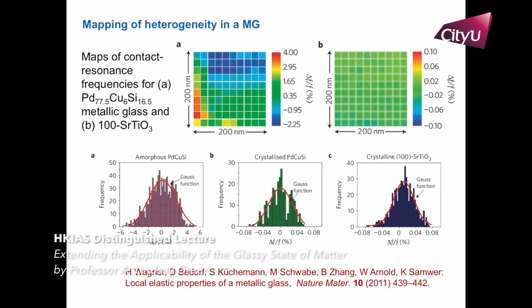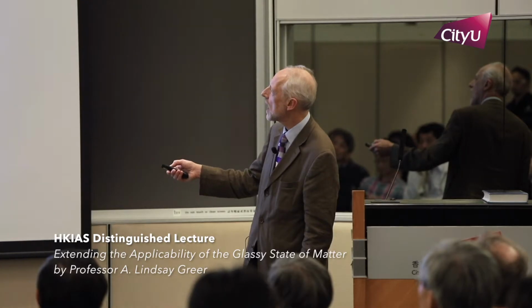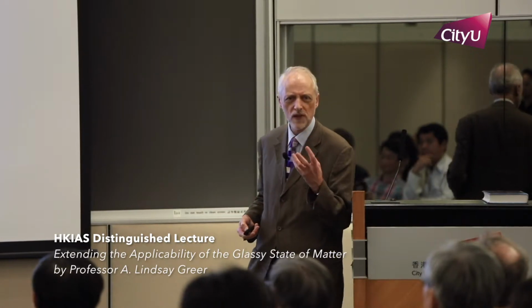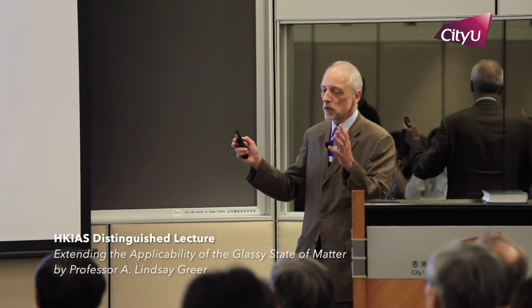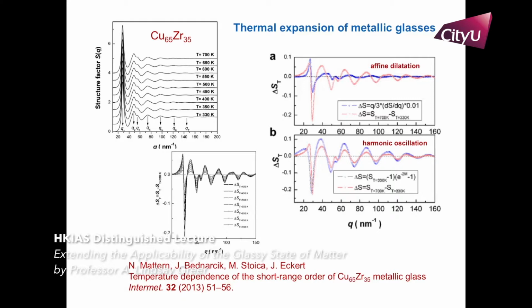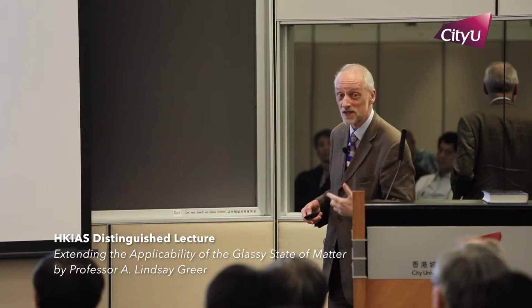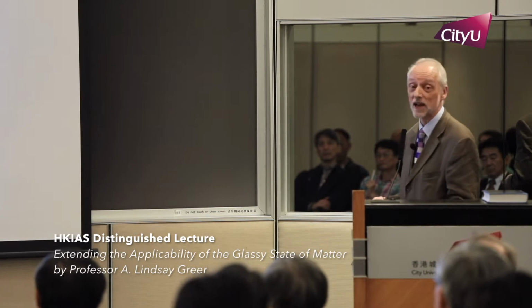Given that it is heterogeneous, it's then not so surprising, perhaps, that if you look at the structure of a glass, here, of course, you've got diffraction data at different temperatures, and you go to lower and lower temperatures, you're getting what should be simple thermal contraction. And if it were thermal contraction in a simple way, it would be like you would just take a photograph of the structure, and as you go down in temperature, you have the photograph at somewhat lower magnification. So everything would scale perfectly. You'd have affine displacements. But when you look at the differences between these curves, and you compare it with what you would predict if it was affine, it doesn't work. Classically, we'd say in the picture where you're cooling a liquid to form a glass, the liquid structure changes with temperature and the glass structure does not. But that seems to be too simple. The glass structure is also trying to change with temperature, and in fact it damages itself as you change the temperature, and in that way you accumulate excess energy.